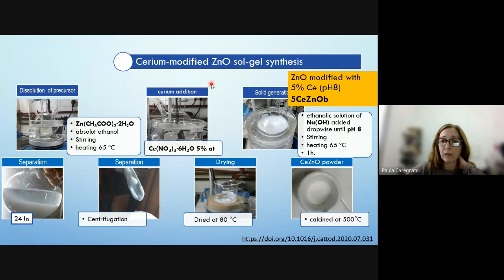Another material obtained by Sol-Gel synthesis is the following. The same precursors were used, zinc acetate and cerium nitrate, and the solid was generated by adding dropwise an ethanolic solution of sodium hydroxide until the pH of the reaction mixture was equal to 8. The following steps to obtain the solid were the same as before. This material is named 5-cerium zinc oxide basic because of the basic media.